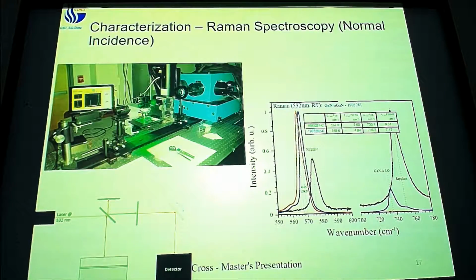We filter out the green light because it's our laser. We don't really care about it. We just wanted to use it to do something. And we get out the information about the phonon structure. We see where the phonons are, and we see the energy difference between the laser coming in and that phonon. And that's what we were measuring here. And it gives us a clue as to how well defined our crystal structure is, as well as if there's any stress or strain in our crystal structure.